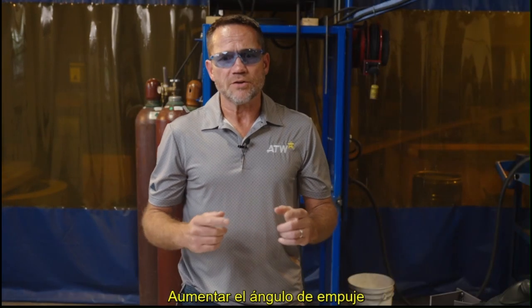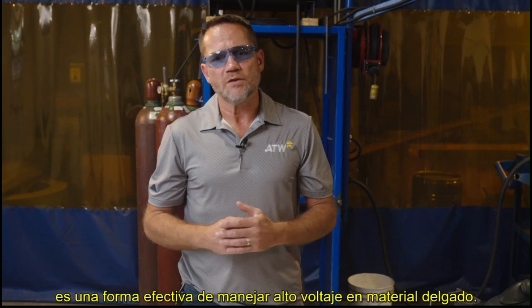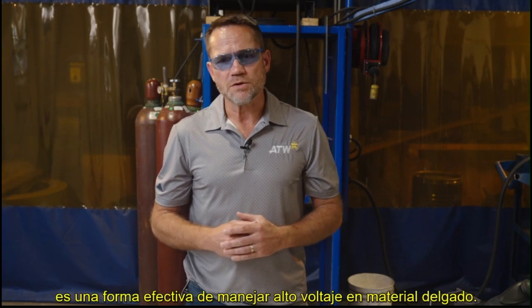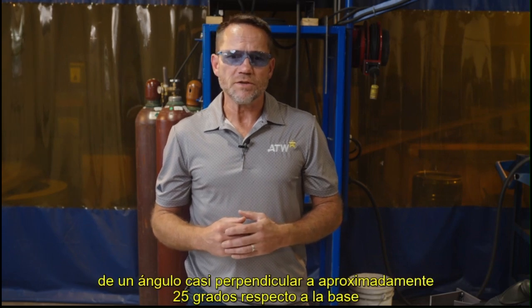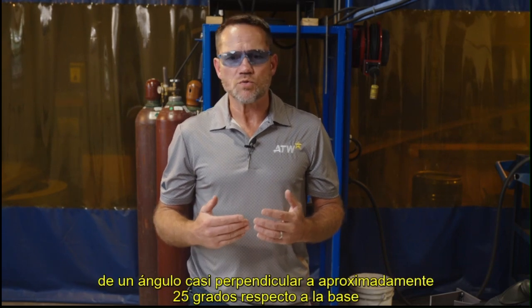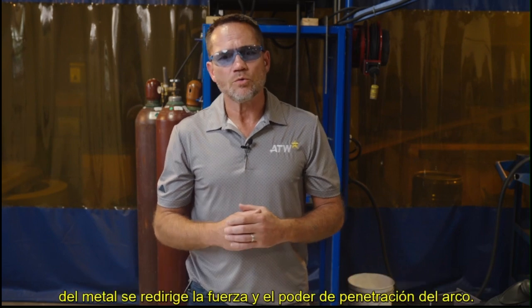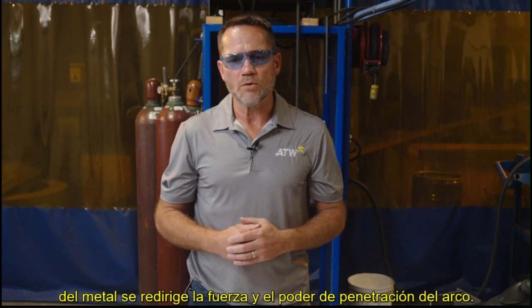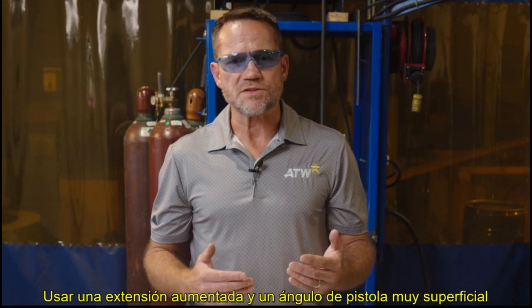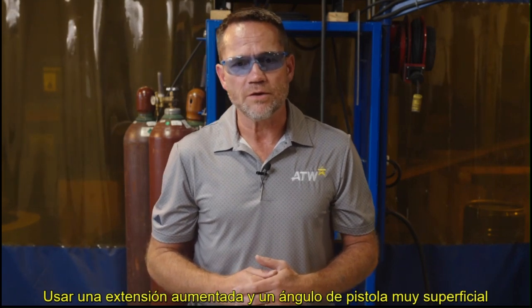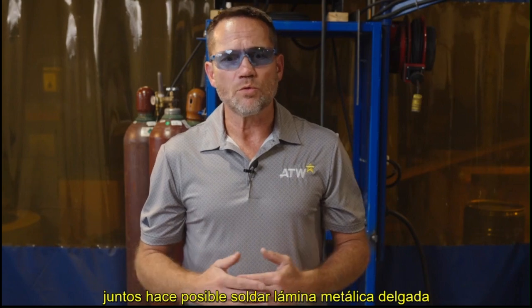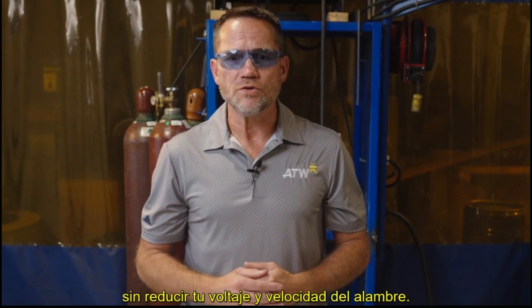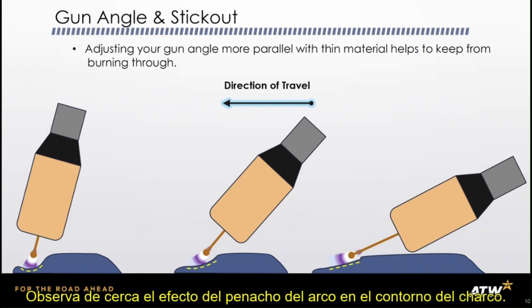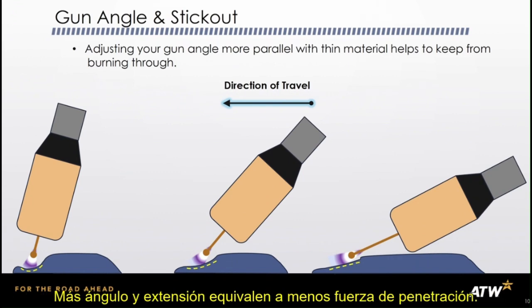Along with stick out, increasing the push angle is an effective way of managing high voltage on thin material. Simply shifting from a nearly perpendicular angle to roughly 25 degrees off the base metal will redirect the force and penetrating power of the arc. Using increased stick out and a very shallow gun angle together makes it possible to weld thin sheet metal without reducing your voltage and wire speed. Look closely at the effect of the arc plume on the contour of the puddle. More angle and stick out equals less penetrating force.